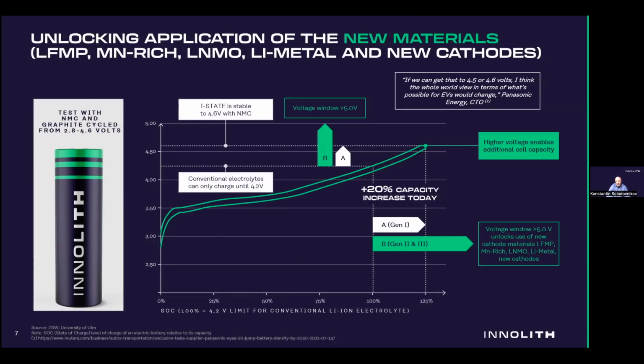With our electrolyte, we can cycle the same cathode and anode materials to higher voltages, provided they stay stable at those high voltages. For example, NMC811, which is a widely used high nickel chemistry, is stable with our electrolyte up to 4.6 volts. And using 4.6 volts, we get access to 100% of lithium that is stored in the cathode material. So we are not creating new materials, we're improving efficiency of use of those materials that are already in the battery cell. And this 20% of lithium is normally not accessible with organic solvents, and it is basically dead weight in the battery cell that then results in higher cost and lower efficiency in operation of a battery cell.